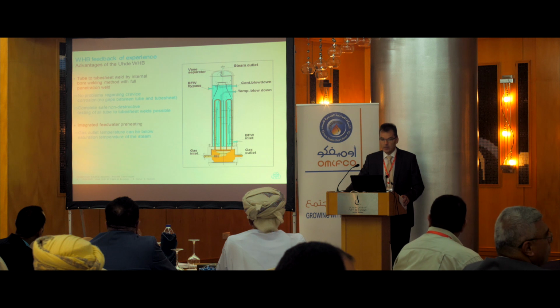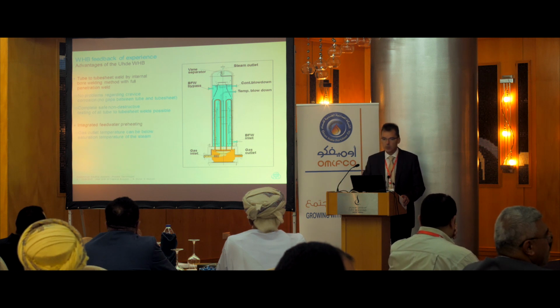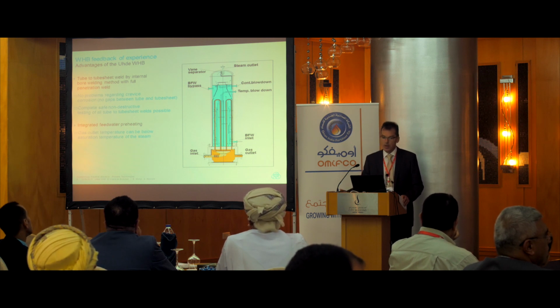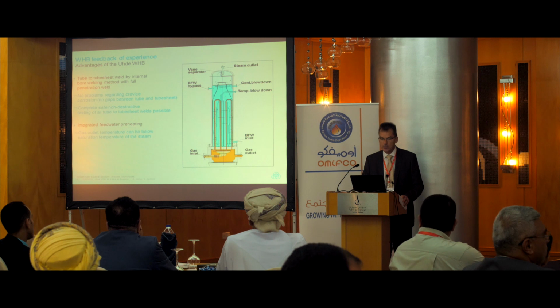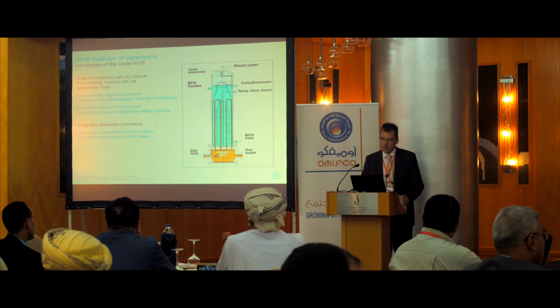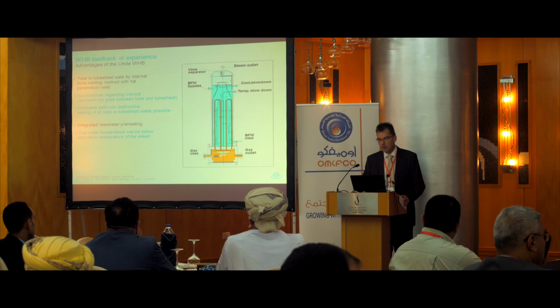Other features are tube-to-tube sheet weld by internal bore welding method with full penetration weld. I will show you one slide, just a picture, so that you see what this so-called internal bore welding is. That means no problem regarding crevice corrosion, because there are no gaps between tube and tube sheets. In other designs, the tubes will go through the tube sheet, and even if you roll them on the tube sheet, you will have small gaps, which risk that impurities will collect there and you get corrosion in this area.